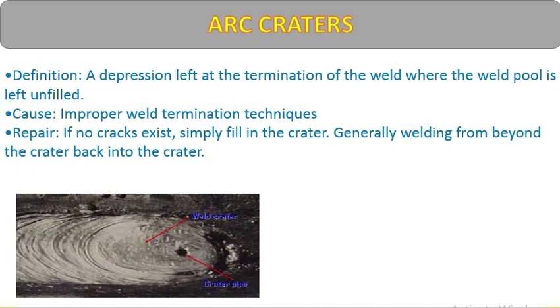Arc craters — a depression left at the termination of the weld where the weld pool is left unfilled. At the end of welding, unfilled conditions create the crater. Cause: improper weld termination technique — the start and stop technique is not done correctly. Repair: if no crack exists, grind the area, check by LPT or DPT, and if there is no crack, simply fill the joint and check again by LPT or DPT.